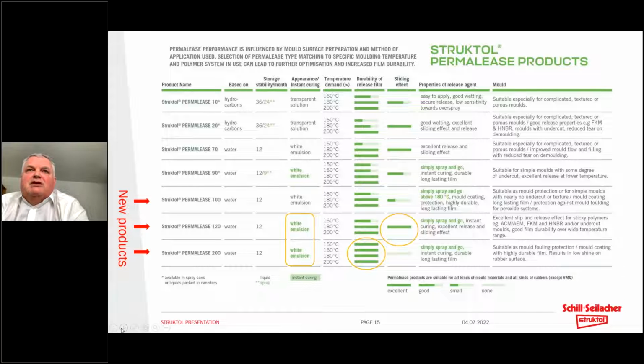We talk about durability of the release film, and you see the central column, if you like, with the horizontal bars. This is the ability of the coating to withstand multiple moldings at different temperatures. And some coatings are more effective or less effective at different temperatures. Some of the latter coatings that we've produced, more recent coatings, are much more flexible in terms of the wider range of molding temperatures and their ability to remain durable both at low and high temperature molding applications.